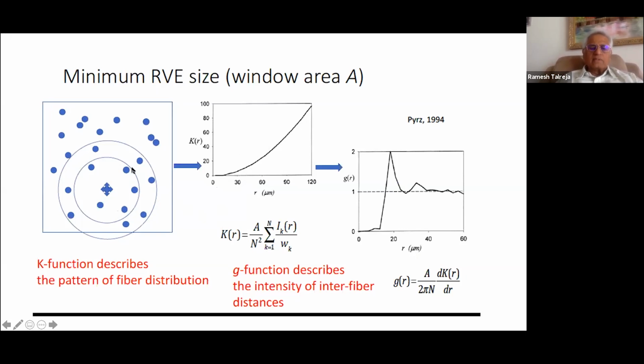If I give you one distribution of fibers, which is non-uniform, and another one that is non-uniform, these K curves will be able to show differences between those. So if it's a uniform distribution, the K will have a very different appearance. That's not enough for quantification. So a G function has been proposed. What that does is essentially from here to derive the variation, that is how the interfiber distance is changing. And when you plot that against the r, what you find is that for small values of r, that's in the close neighborhood of fiber, you have a lot of undulations. And as you go further and further, it stabilizes.